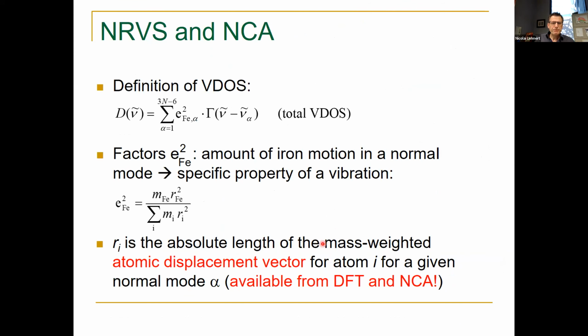And again, going back to this equation here, right, the E² factor can be calculated from normal coordinate analysis, so from simple force field calculations. And then, of course, as you also saw from Volker's presentation, you can use DFT and then calculate the E² factors. And then from that, you can calculate your vibrational density of states. And this is something that is also really remarkable, right? Because when you perform these kinds of normal coordinate analysis, vibrational analysis, in the case of IR spectroscopy or resonance Raman spectroscopy, you cannot calculate vibrational intensities. You can calculate energies and frequencies and shifts with isotope labeling, but you cannot calculate the intensities. But for NRVS, you can, right? And so that provides a whole other level of scrutiny in order to refine your vibrational simulations of the data.